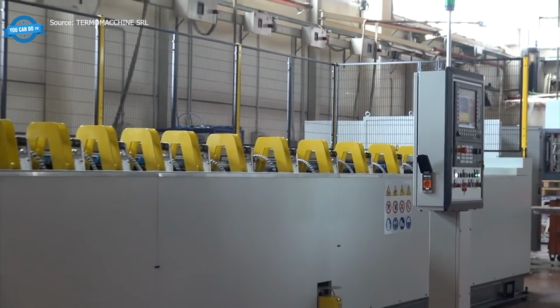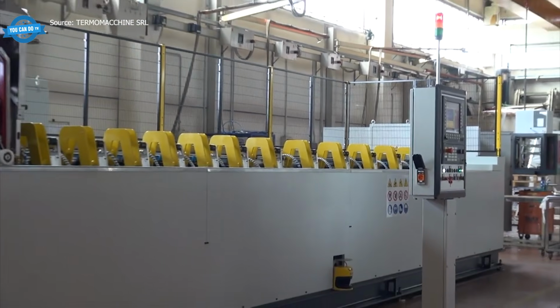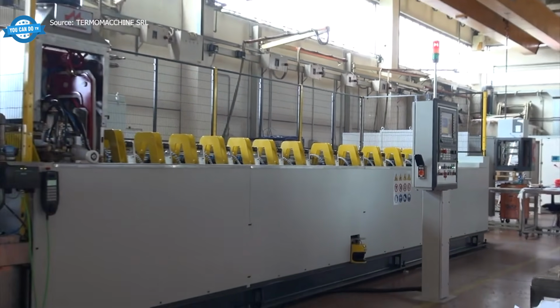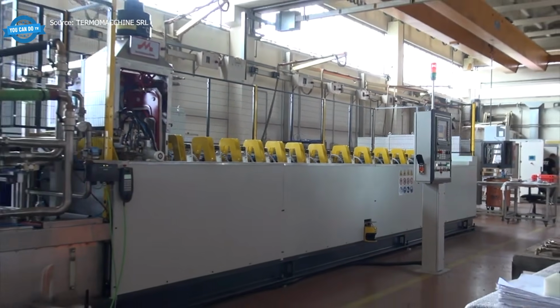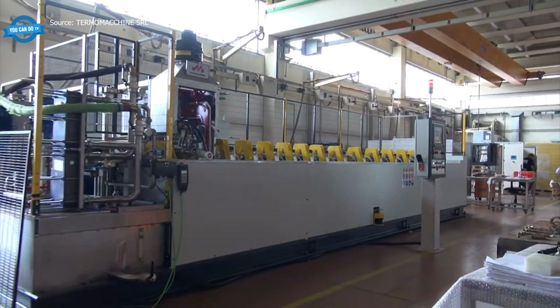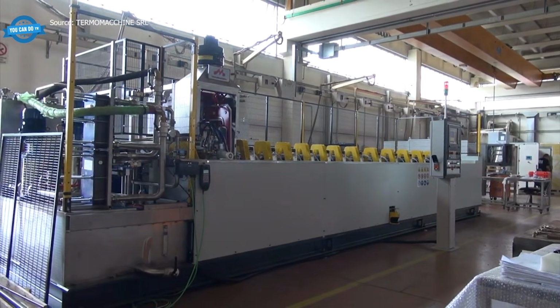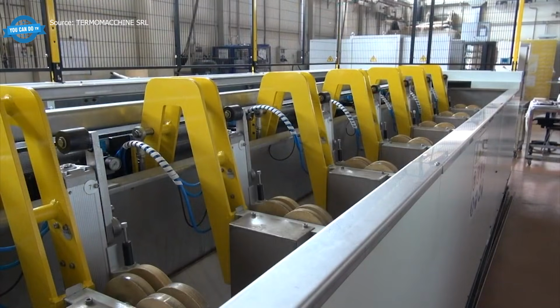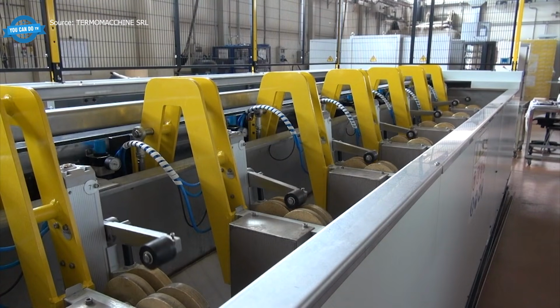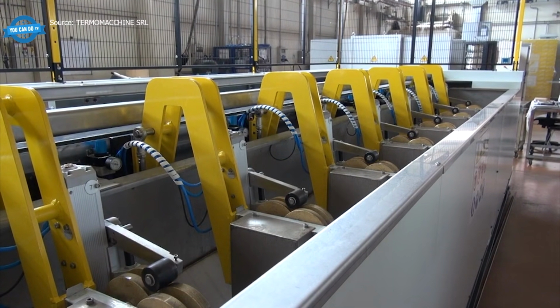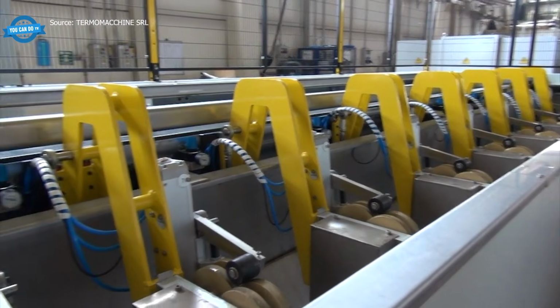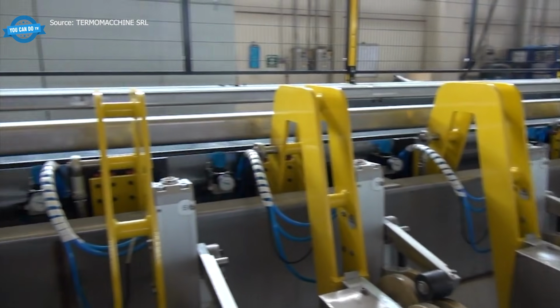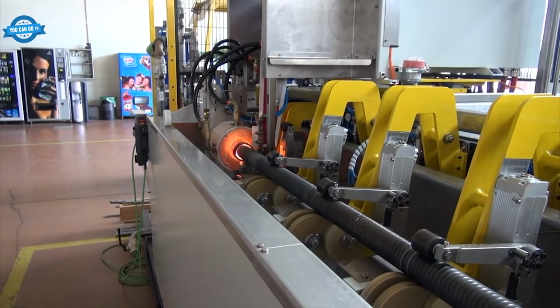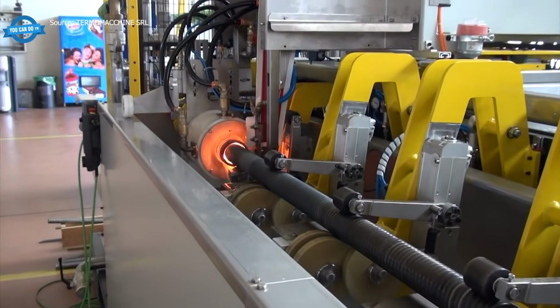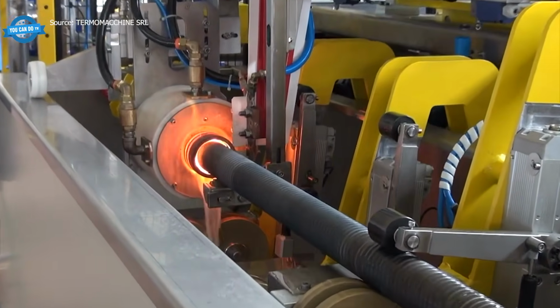A ball screw is a shaft with a helical groove that carries recirculating steel balls, and it has to be hard in exactly the right places. Diameters run from 9 mm up to 65 mm, lengths up to 6.2 meters. The induction coil scans along the shaft at 15 to 35 mm per second, while a 150 kilowatt medium-frequency generator drives the heating. The groove surface reaches hardening temperature in seconds, then a spray quench locks it in.